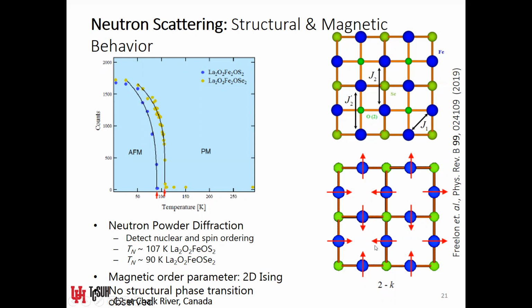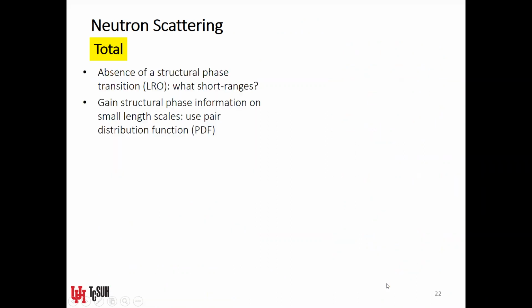In addition to that, we find that these insulators have a double striped antiferromagnetism, in close similarity with a lot of the iron-based superconductors. And so in the lower right corner, we're attempting to show there are spin density waves that are orthogonal to each other that represent this double stripe nature of the antiferromagnetism in these materials.